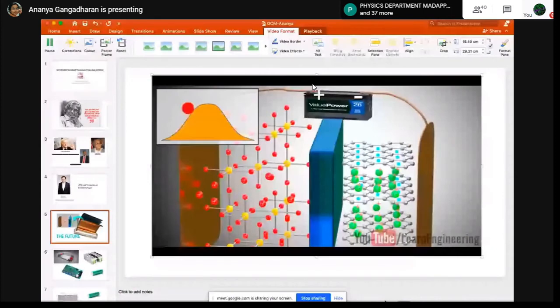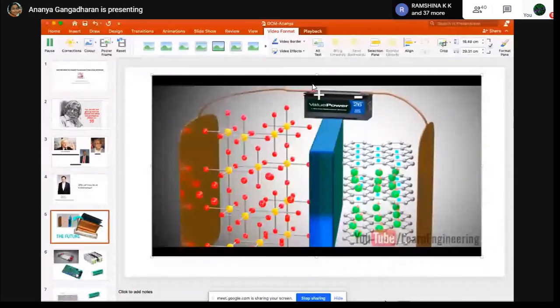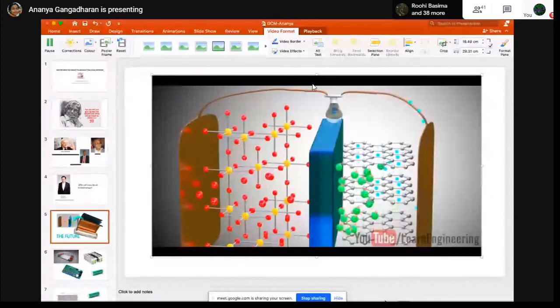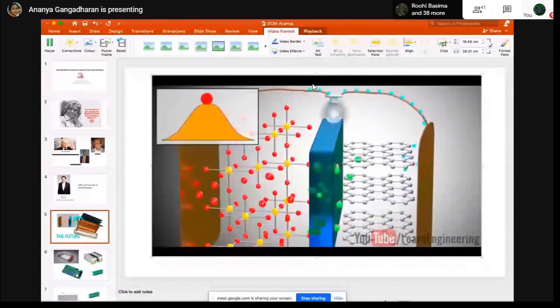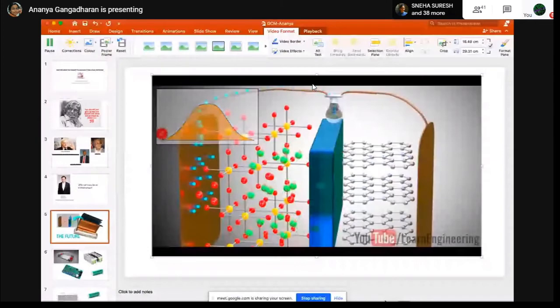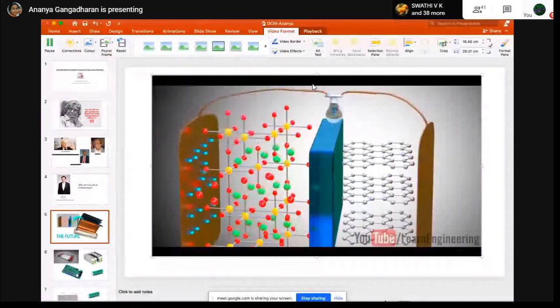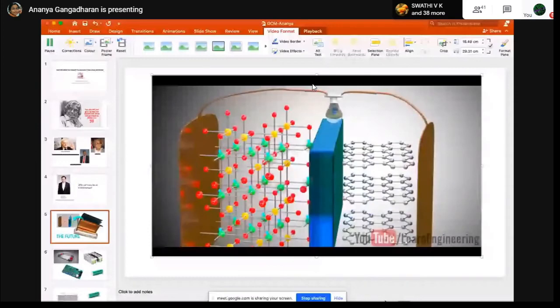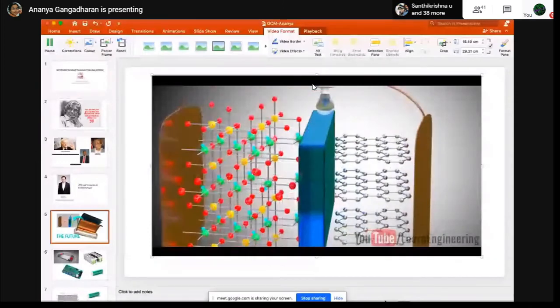As soon as the power source is removed and a load is connected, the lithium ions want to go back to their stable state as a part of the metal oxide. Due to this tendency, the lithium ions move through the electrolyte and electrons via the load, just like sliding down a hill. Thus, we get an electrical current through the load. Please note that the graphite does not have a role in the chemical reaction of the lithium ion cells. Graphite is just a storage medium for lithium ions.